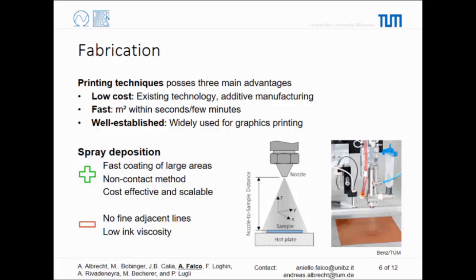It's a non-contact, non-destructive method, and it's an intrinsically additive method, so we are just stacking up, we're not removing material, which leads then to a reduction of the wasted material when we're producing something. Of course, we are not able to have very fine lines, so what we could achieve with lithography or with inkjet printing, you cannot do with spray deposition.